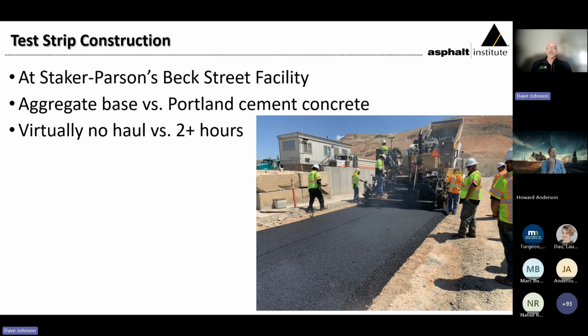Notable differences, as we mentioned, we're going to be paving essentially in a bathtub out at Wendover, surrounding the mix by Portland cement concrete in that milled area. Here, it's truly an unprepared aggregate base. That's their scale that we see in the background. A lot of trucks through the years have gone through there. It is very, very well compacted, but their preparation was simply to run a blade across it and then broom it and then pave it. There is no haul on this, so instead of that 2-hour haul, it's virtually a 0-minute haul.